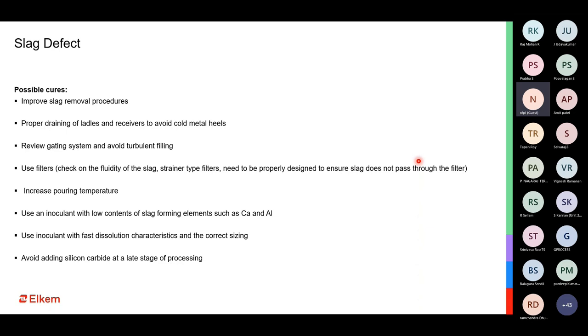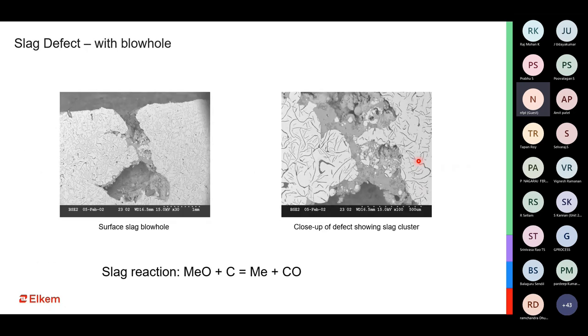Just as one example, avoid adding silicon carbide at a late stage of processing, because silicon carbide as such has a lot of impurities. Commercially available silicon carbide has about 15% impurity in it, and all these impurities have very high melting temperatures. Therefore, they can stay undissolved and can appear as slag in the casting. So basically what happens is the metal oxide can combine with the carbon to form metal and carbon oxides, which try to escape as a gas, thereby giving you a slag inclusion defect as well as a gas defect.